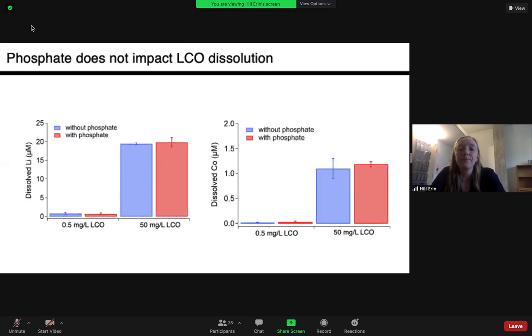My group made solutions of concentrations 0.5 and 50 milligrams per liter of LCO in moderately hard water or moderately hard water with Na2HPO4, which is the red with phosphate on those plots. And at both concentrations of LCO, the solutions with and without phosphate do not have significantly different levels of dissolved lithium or cobalt, which suggests that the phosphate doesn't impact the release of lithium and cobalt from LCO.